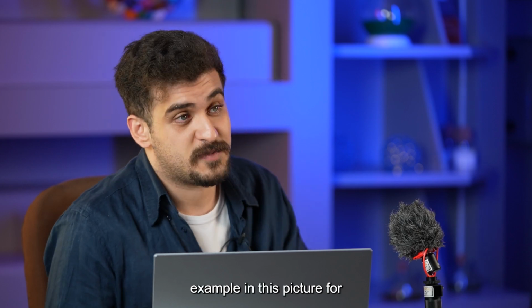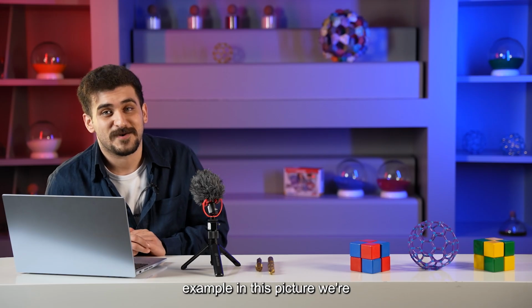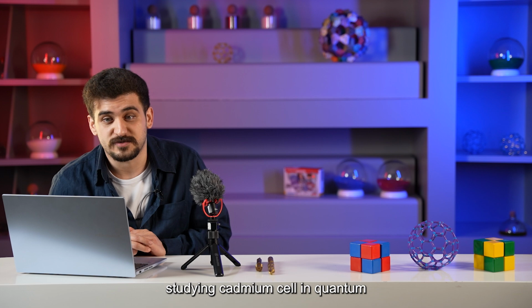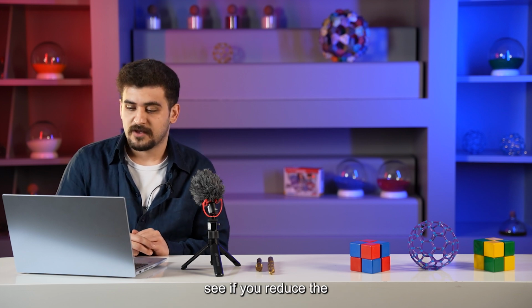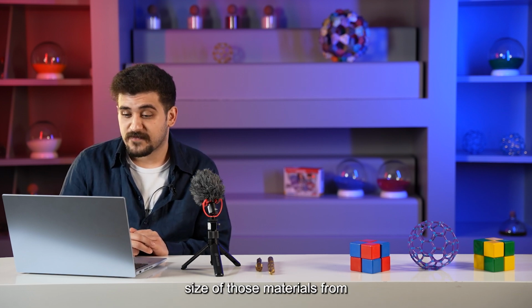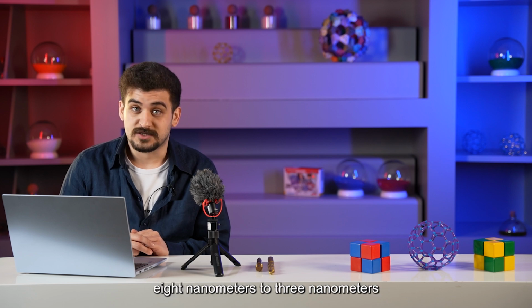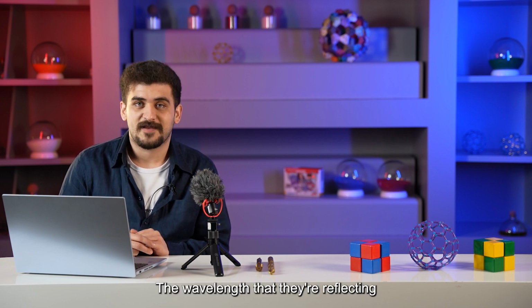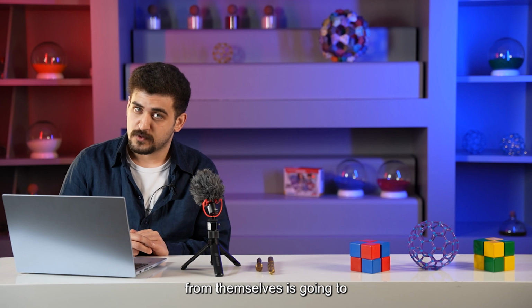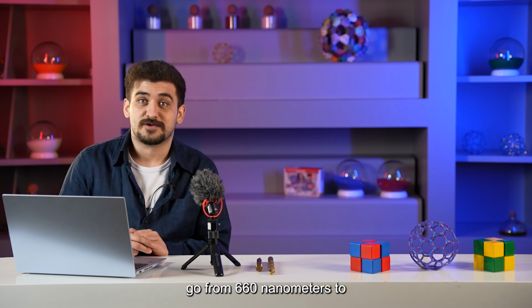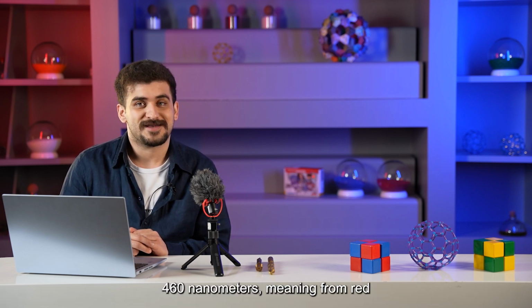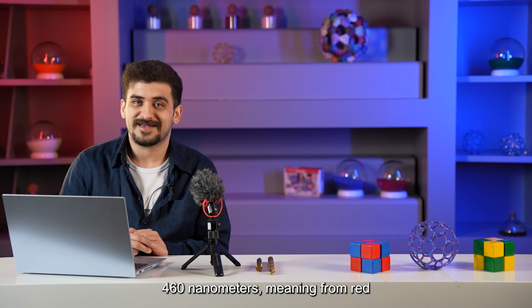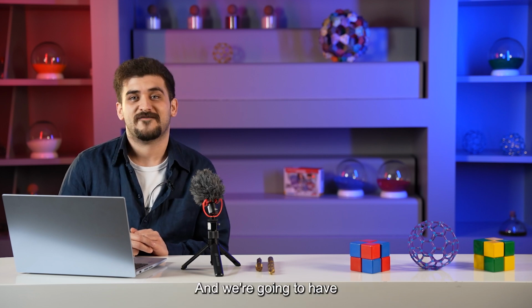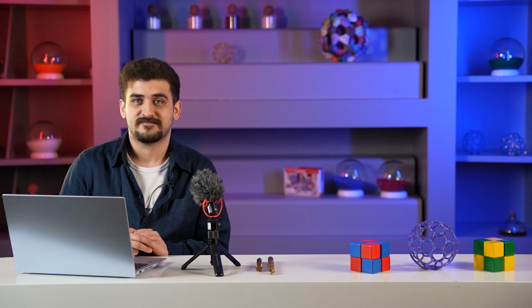Well, as you can see in the picture beside it, if you reduce the size of the material you're studying, for example in this picture we're studying cadmium selenide quantum dots, if you reduce the size of those materials from 8 nanometers to 3 nanometers, the wavelength that they emit goes from 660 nanometers to 460 nanometers, meaning from red to blue, and we have a shift in the color.